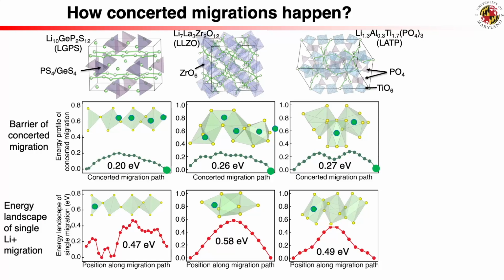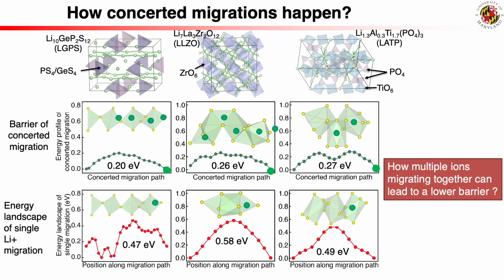What do you mean? They also calculated the energy landscapes for single lithium-ion migration, and they found much higher barriers. Higher? Like how much higher? 0.47 electron volts for LGPS. Wow, that's more than double. Yeah, 0.58 for LLZO, and 0.49 for LATP. So those are way higher than the barriers for concerted migration. Right, which means the traditional model of single ion hopping can't explain the fast diffusion we see in these materials. Because it would predict much slower movement. Exactly. So something else is going on.